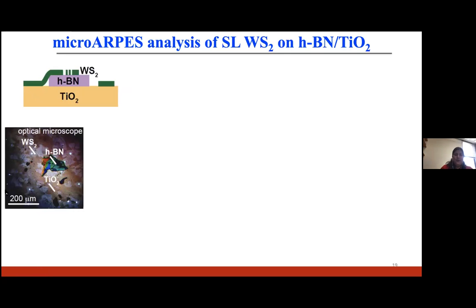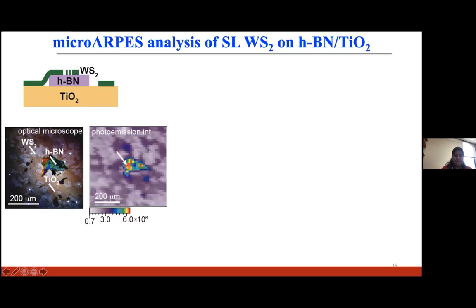Okay, so here is the optical image of our sample. And here's the corresponding photoemission intensity map of the same area. And so here at each pixel, we actually measured the dispersion of our sample.